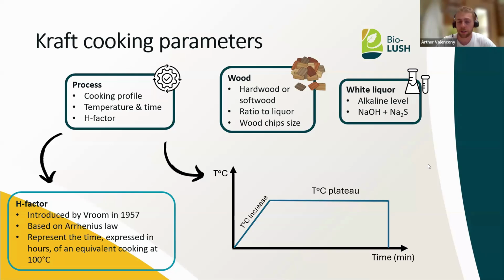Okay, so there are different parameters in this kraft process. Regarding the process first, the cooking profile is interesting to see, with the temperature and time. To do so, we can talk about the H factor, which is an interesting parameter. The H factor was introduced by Vroom in 1957. It is based on the Arrhenius law, and it takes into account temperature and time to establish a control parameter for this cooking. It represents the time, expressed in hours, of an equivalent cooking at 100 degrees Celsius. With that, we can compare a fast cooking at high temperature, for example, with a longer cooking at lower temperature.